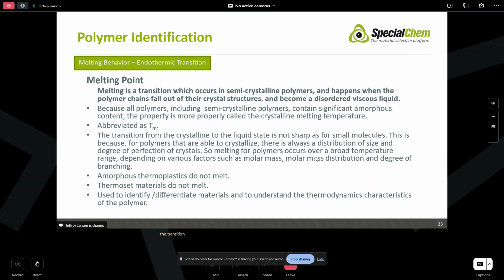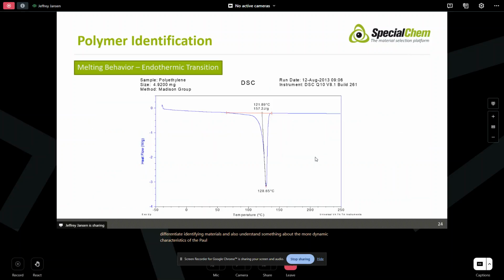The transition from crystalline to liquid state is not sharp as it is for small molecules. If we look at the melting point of, say, an organic monomer, we're going to see a very sharp melting point, okay? With polymeric materials, because there's a variation in molecular weight and the organization of the crystals may not be the same across the entire polymer. They're not as organized, they're organized differently. We're going to get this broad melting point, okay? Amorphous thermoplastics don't melt. Thermoset materials don't melt. And that melting point can actually be used to differentiate or identify materials and also understand something about the thermodynamic characteristics of the polymer. Okay, so here's polyethylene, very simple molecule.